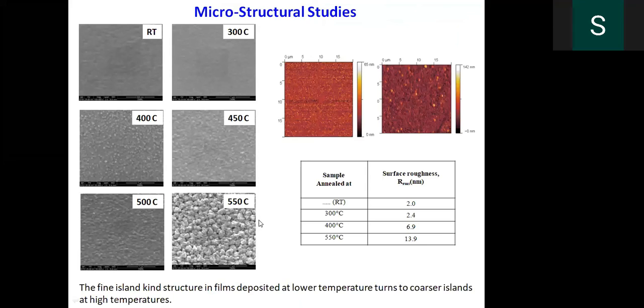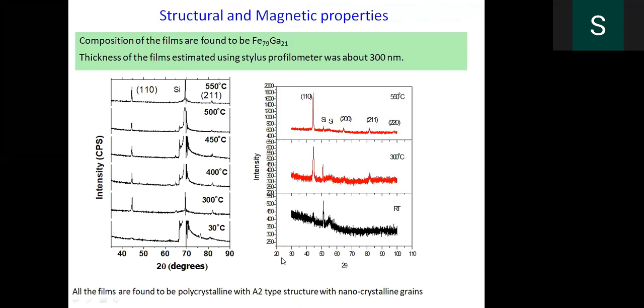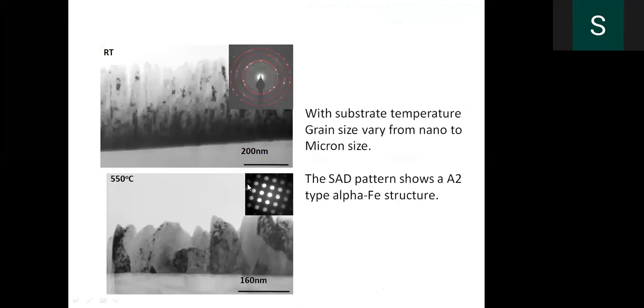So we have also adopted growing at different temperatures. When we grow at different temperatures, we got globular kind of features, and the roughnesses are found to be very high. And we could see, although all of them form in A2 phase, the presence of some other phases could also be identified. And these are the cross-section transmission electron microscopy images which we have carried out on these films.